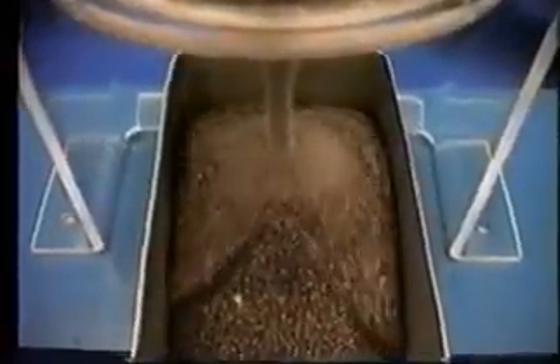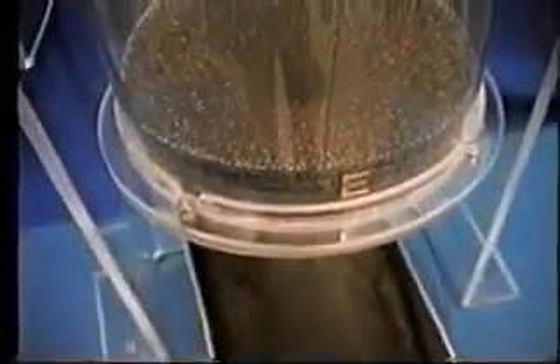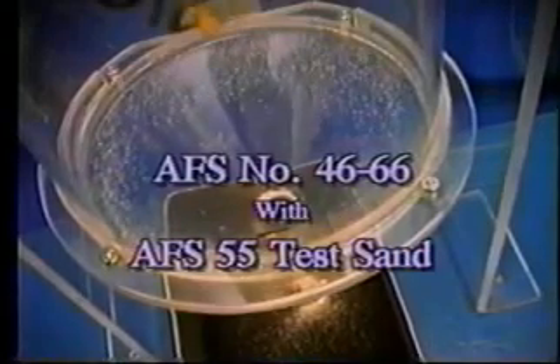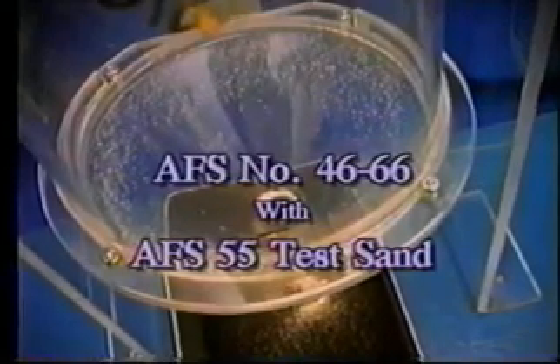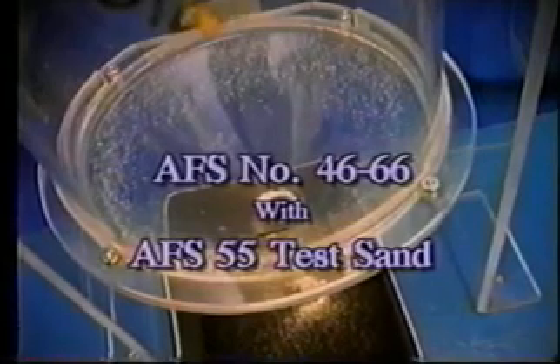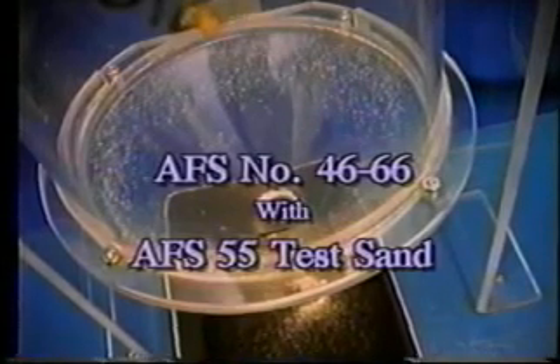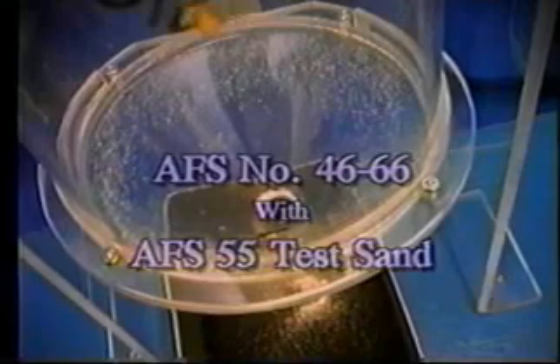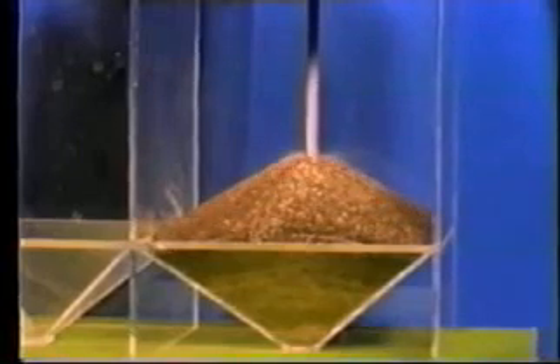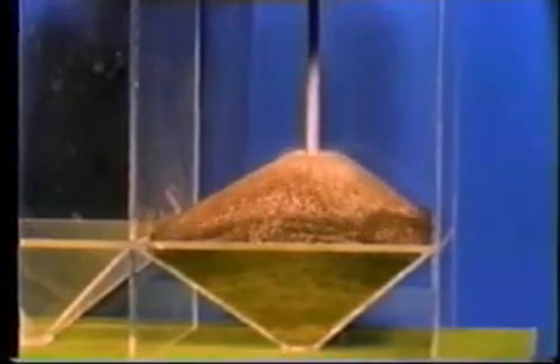After the fine sand is gone, coarse sand falls into the funnel and discharges rapidly. This results in a wide variation in the screen distribution of the sand exiting the bin. Variations from an AFS number of 46 to 66 were experienced with the 55 AFS test sand. A plexiglass model of a railroad car was also fabricated, and similar loading tests accomplished as shown here.